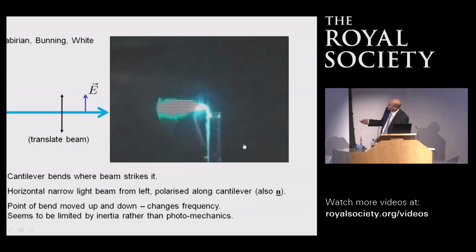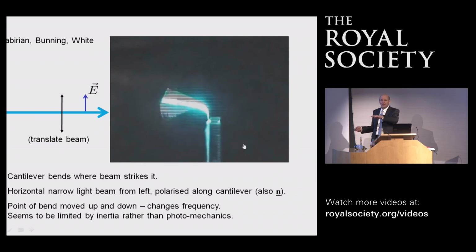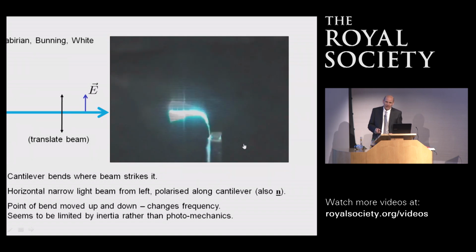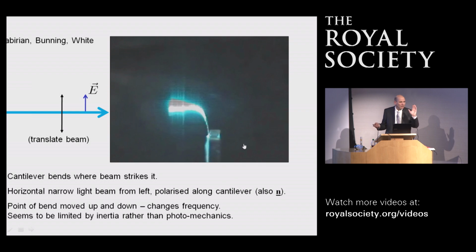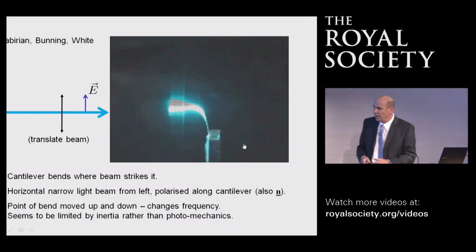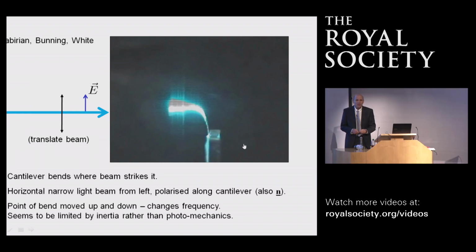When it bends forward, it occludes the light, and it's no longer being forced to bend, it straightens up, and as soon as it's straight, then it's again exposed to the light, and it bends down again. And it happens at about 270 hertz, so it's a bit fast, and the camera doesn't follow it very well, but it's just doing this extremely fast. This is from a group in the US Air Force, and they are wanting to actually make little flying machines out of these powered by light.